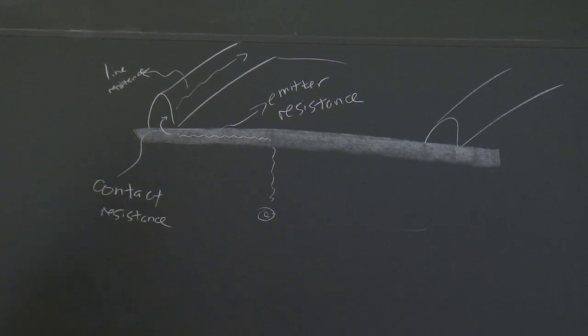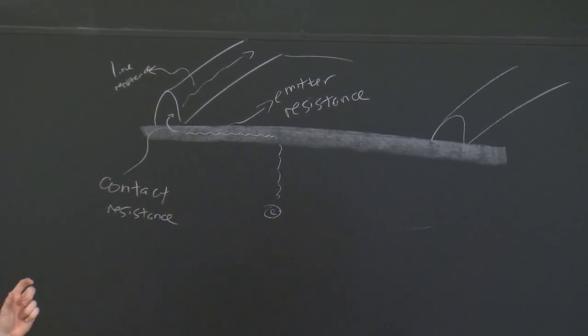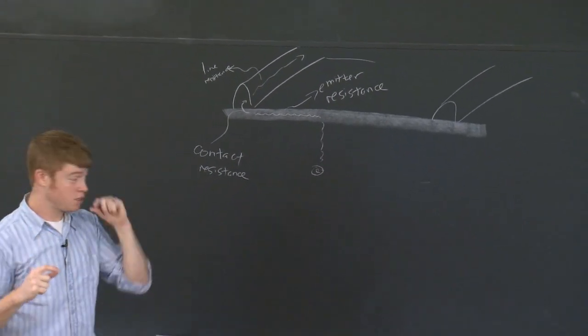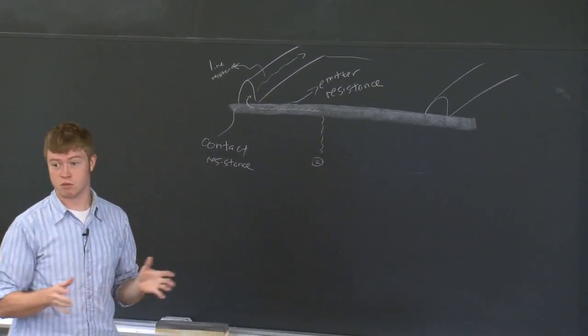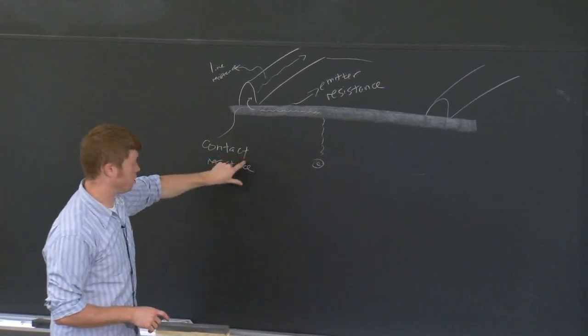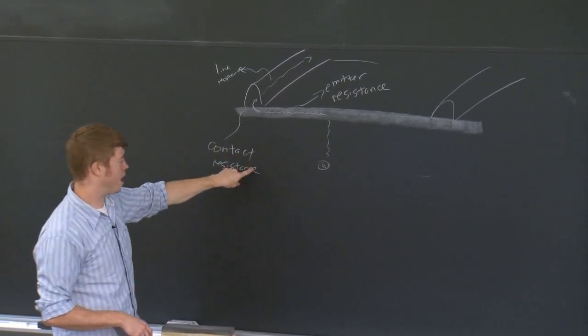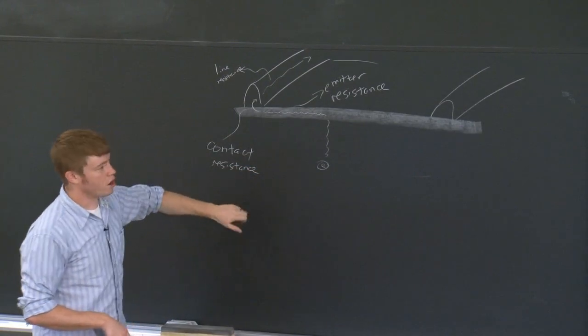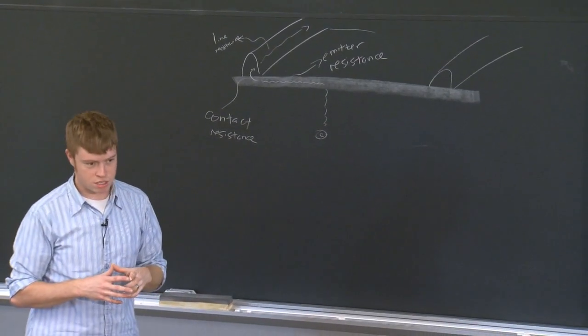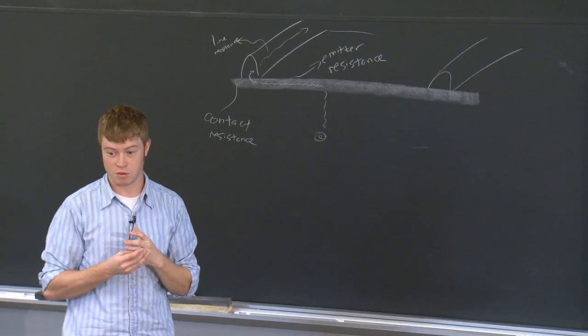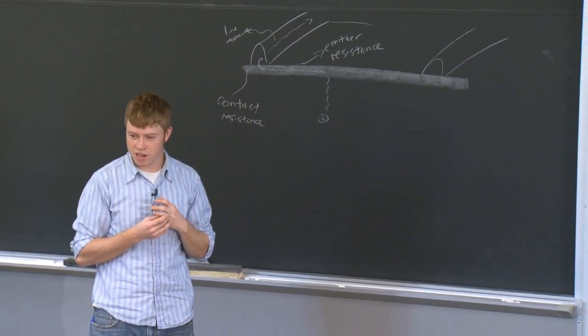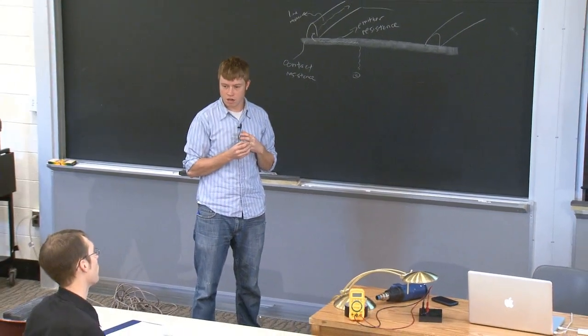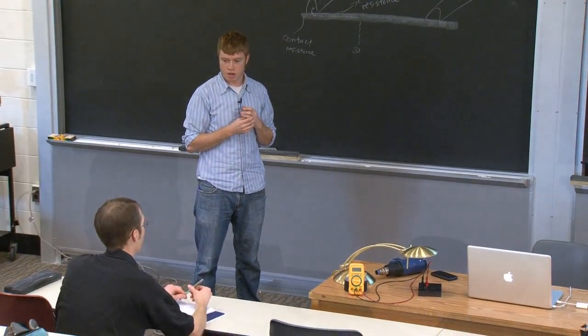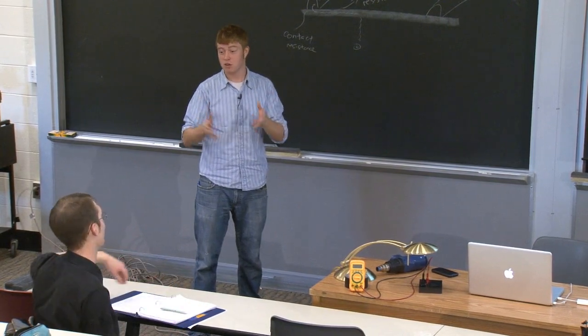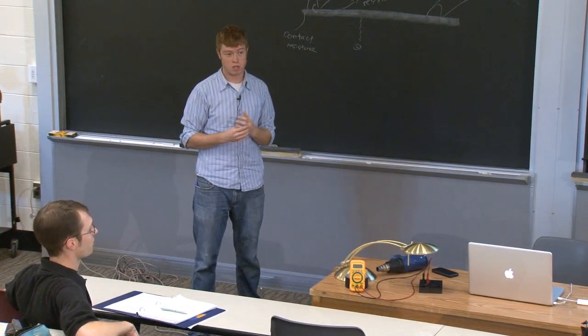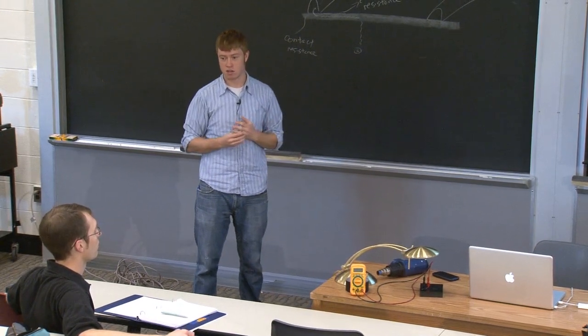And I think what's really limiting us, because when I looked at both the shallow and deep emitters, the series resistance didn't really have any noticeable trends, so I really think that this is what's limiting us completely, is our contact resistance, which is kind of too bad. So one of the reasons I think that that's the case, additionally, is that of the cells that perform the best, I know Joel's did particularly well. I think he had, what was your fill factor? Do you remember? Well, on the one side it was 0.5, and on the other it was 0.64. OK, so one side was better. So again, the inhomogeneity of the measurement was also another indication that our series resistance across the contacts is really poor.